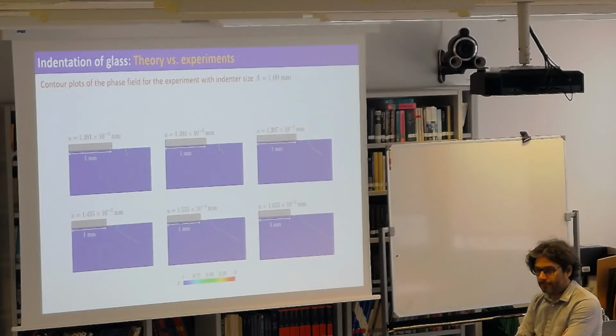It seems to me that this is true once the crack length is large enough, because it's clear you push on the indenter, so you understand that if you push on the indenter, the crack, which is here, is subjected to loading like this, so the crack tip is loaded in shear. But this is true only if the crack length is sufficient, because at the very beginning, because of the boundary conditions, you can only have tension in the horizontal direction. Actually, that's not true.